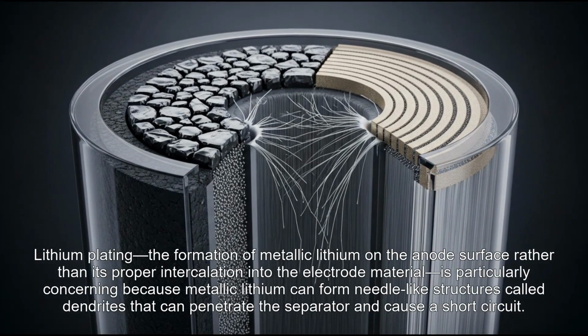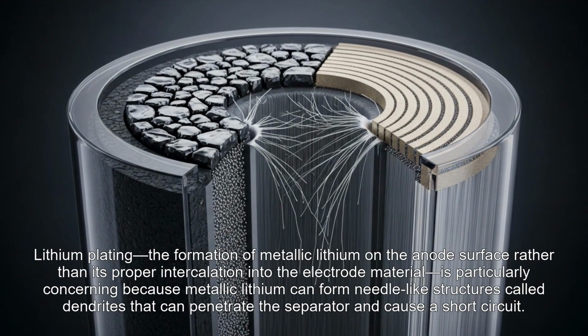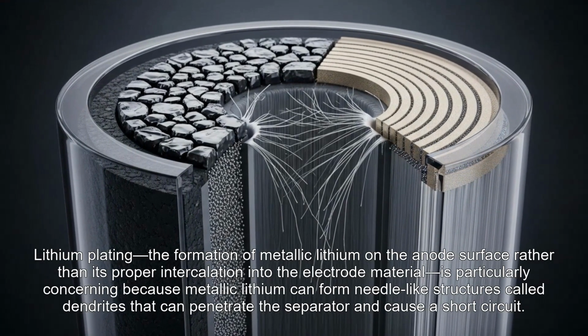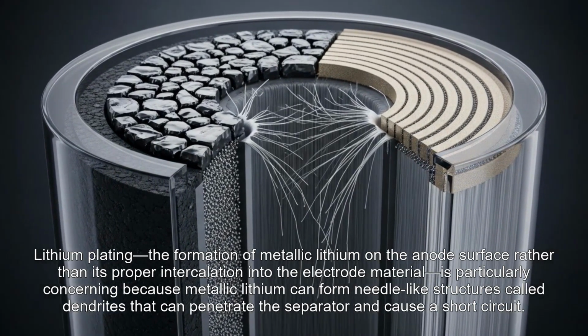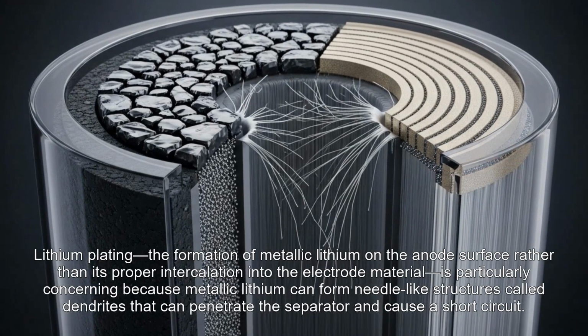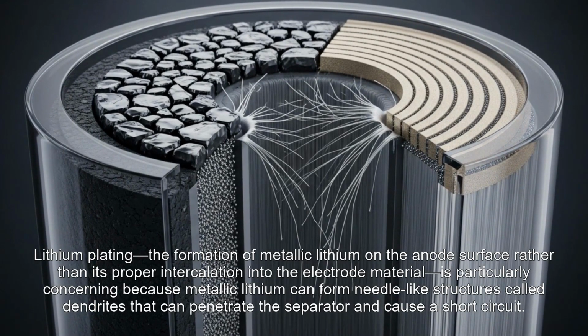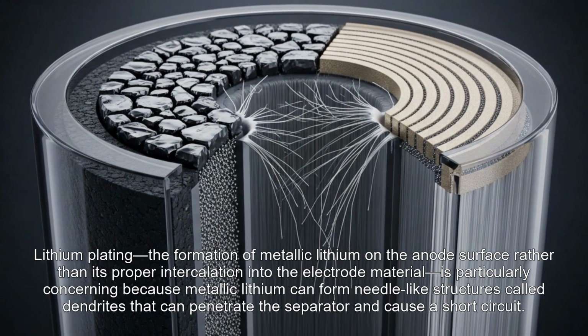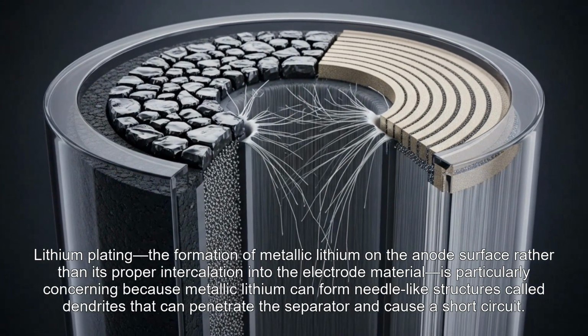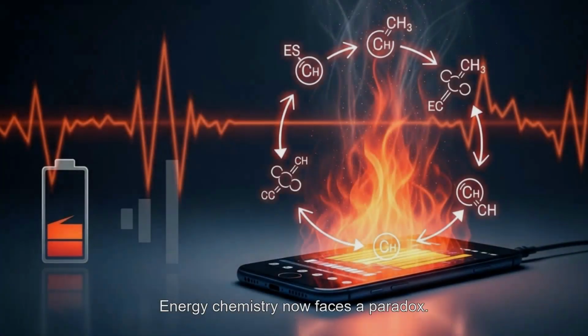Lithium plating, the formation of metallic lithium on the anode surface rather than its proper intercalation into the electrode material, is particularly concerning because metallic lithium can form needle-like structures called dendrites that can penetrate the separator and cause a short circuit. Energy chemistry now faces a paradox.